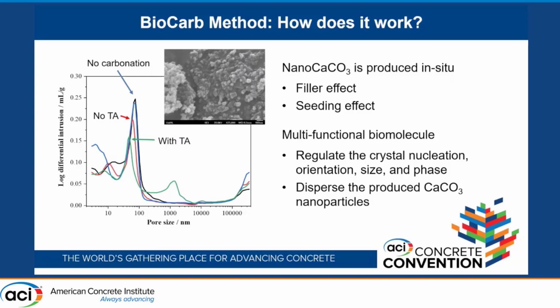Basically, with this process we have nano calcium carbonate produced directly in that slurry. So you have the advantages of having nanoparticles in a concrete mix, which are the filler effect, so you can improve your packing density, as well as the seeding effect. Those nanoparticles can also help you trigger the hydration process and help with your performance. If you look on your left, we have MIP, and you can see, for reference, the two samples with no carbonation. If you carbonate with no biomolecule, you do see a shift towards the left, for a smaller particle size. And once you add the tannic acid, you get even smaller particles.